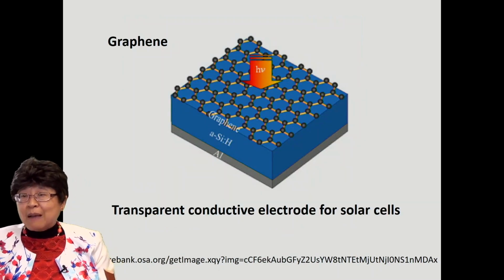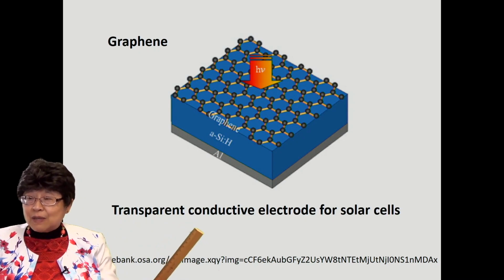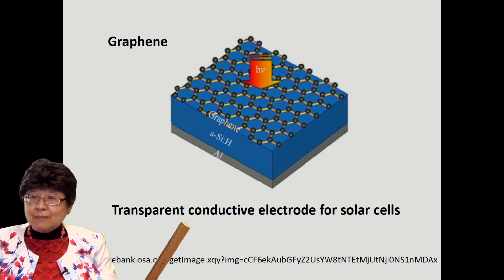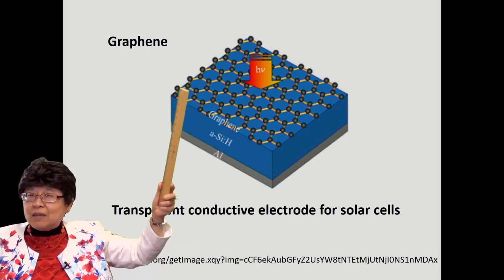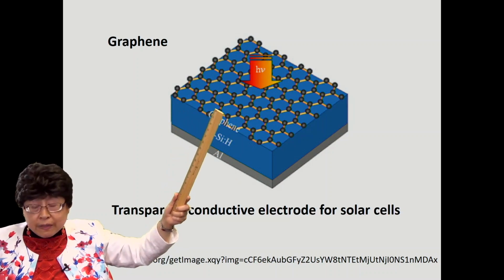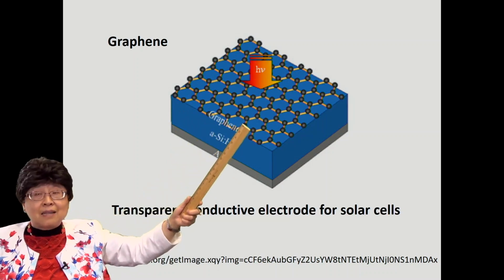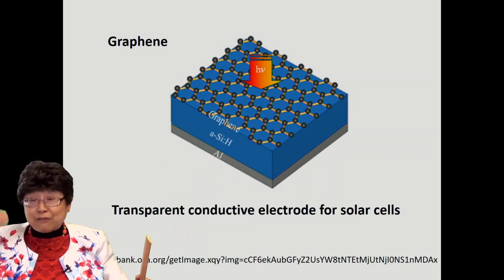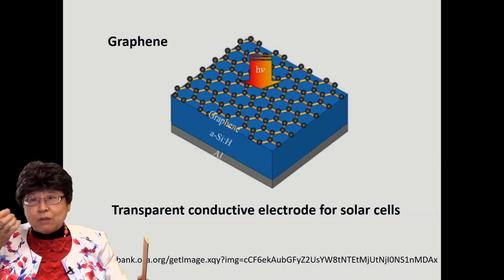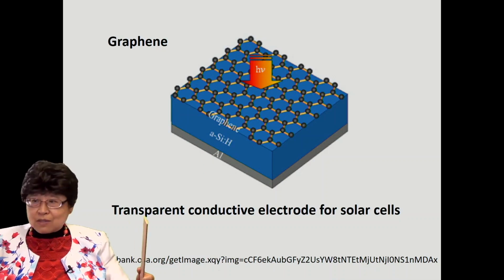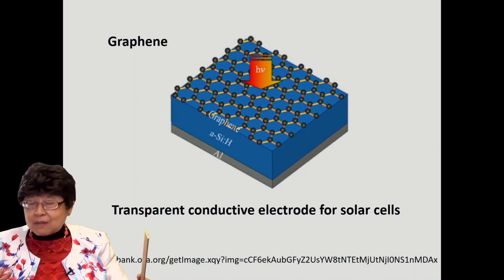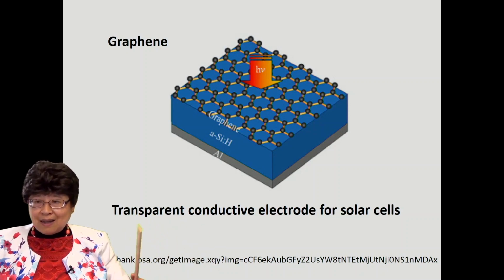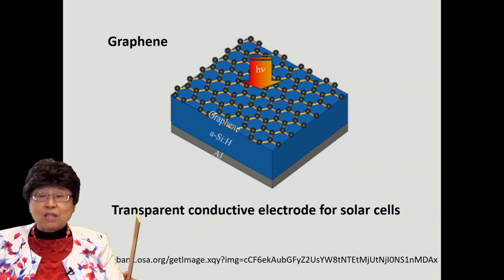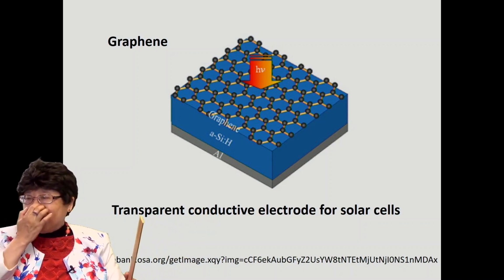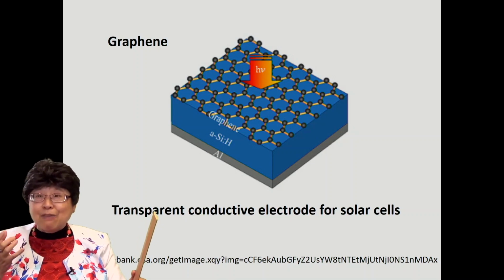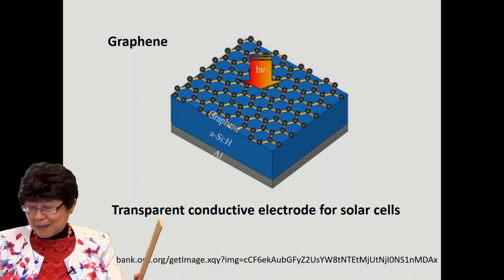However, graphene has some important applications, particularly as transparent conductive electrode for solar cells. And here you see the graphene, just one layer. So it's very, very thin, so thin that light can go through it, so it's transparent. Now for solar cell, you have to have light to be able to go through it, right? But you need an electrical contact so that you can get electricity out of this solar cell, okay? And that's why we need transparent conductive electrode. That's a very challenging combination, both conductivity and transparency. Metals are not transparent, okay? Graphite is not transparent either, it's black, but if it is very, very thin, it's transparent, okay?